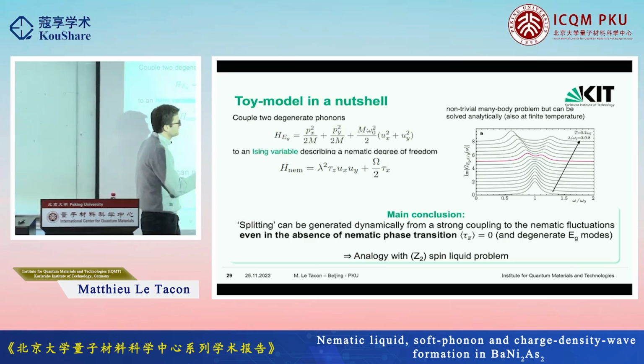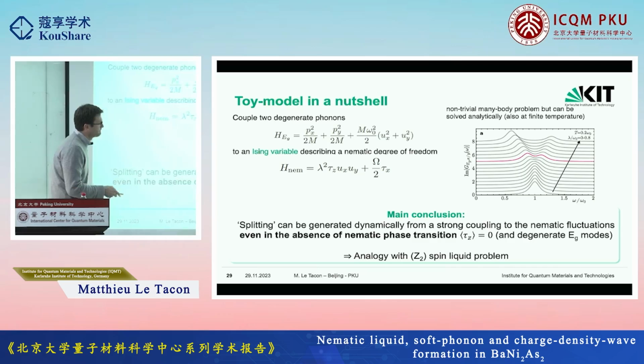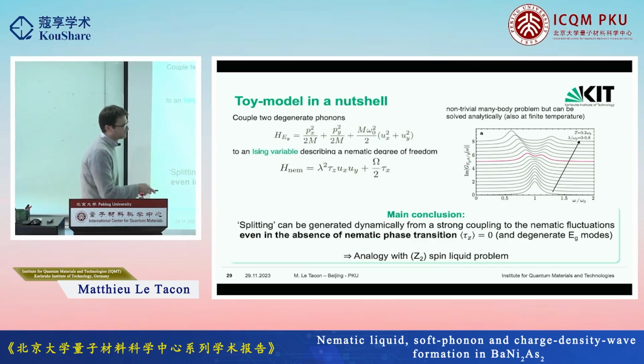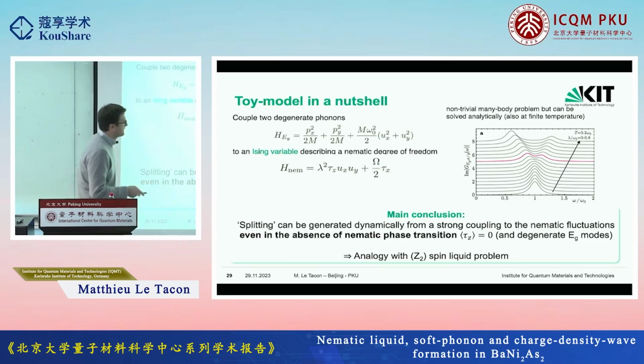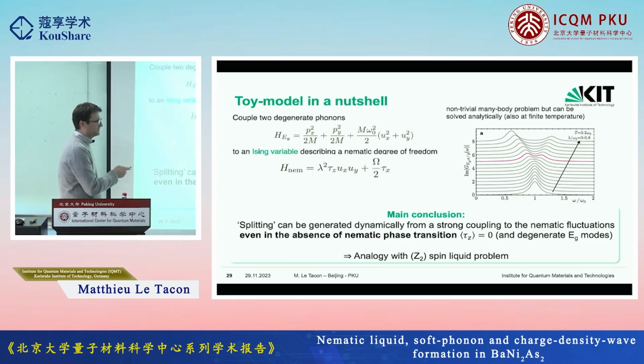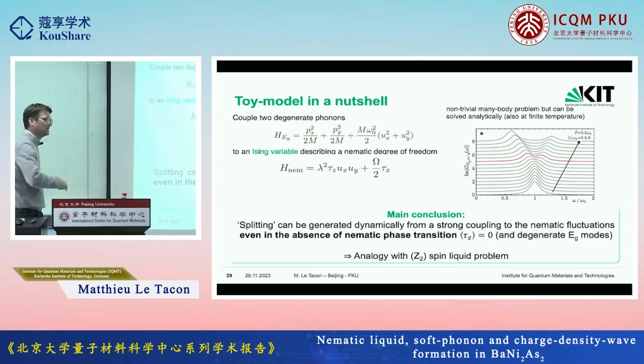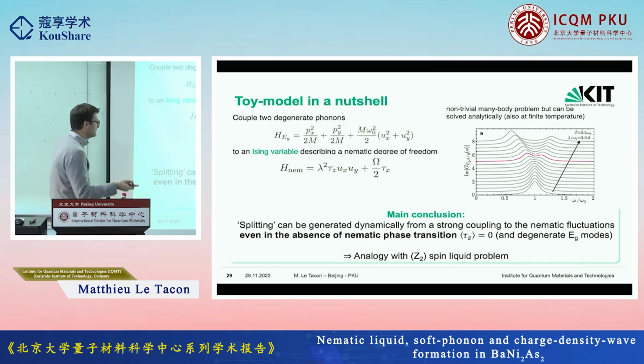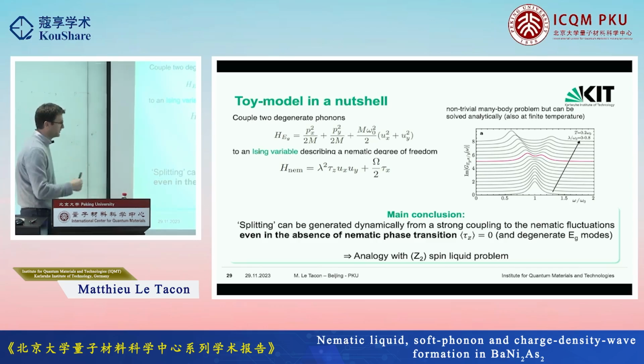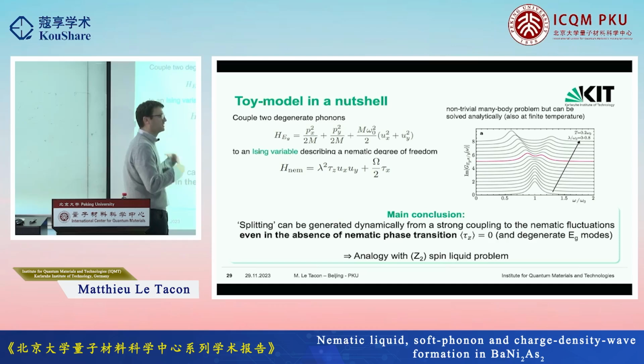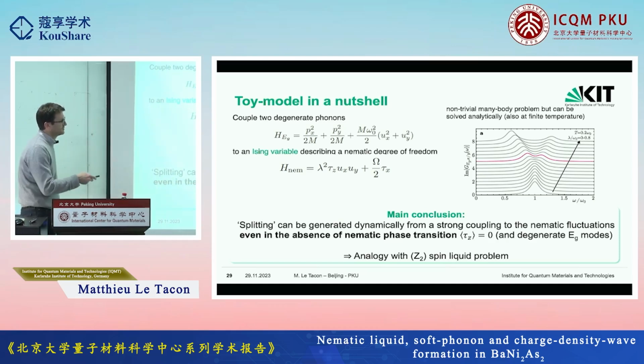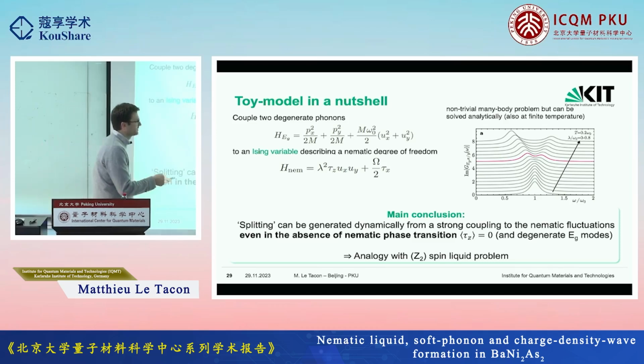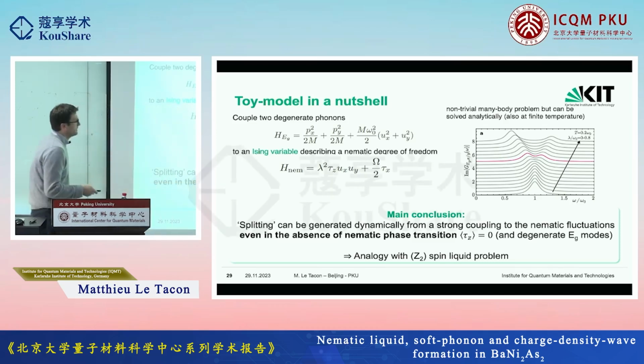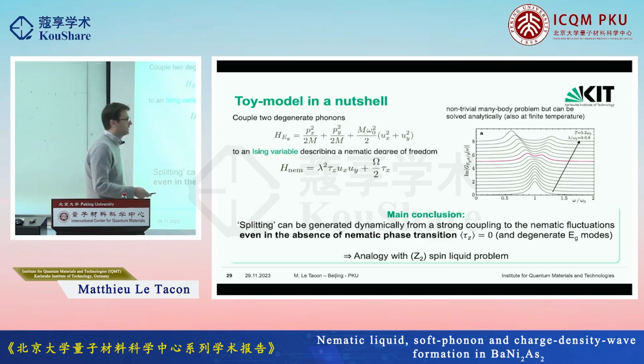And what you see by increasing the ratio of the coupling constant to the mode frequency is that you will see a splitting of the mode. But the splitting that you see occurs when the expectation value of this Pauli matrix tau z is still 0, meaning that you don't have long-range order. So in a regime where your system is still completely fluctuating, there's no long-range order, you can see the splitting of the mode. And again, it's not a splitting in that case, it's just a change of the line shape of the phonon, which reflects this coupling. And of course, if your coupling is too strong, you will go into an actual phase transition, so you will order the system.